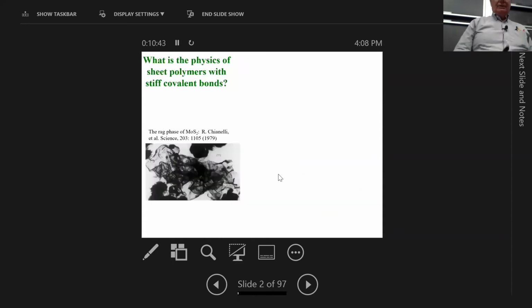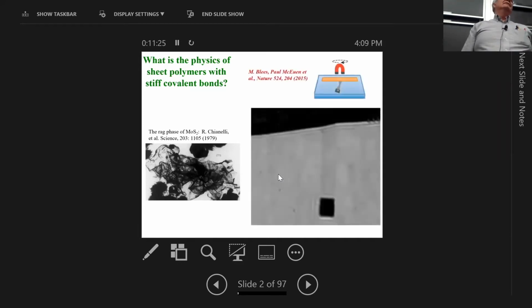Even back in those times, we were quite interested in atomically thin sheets. And this is the so-called rag phase of molybdenum disulfide. And you can see that in this electron micrograph, I presume that's what it is, this is an analog of a sheet polymer, but with stiff covalent bonds. And you can see it sort of looks like a crumpled piece of paper, but it's atomically thin. And we never really found a good system to study back in those ancient times, but along came graphene.